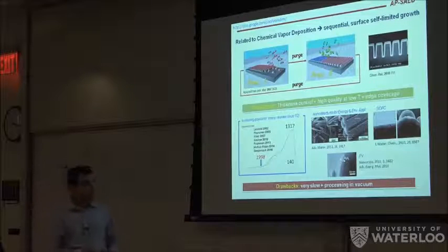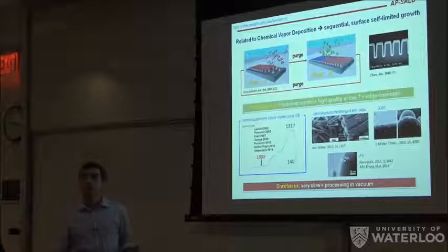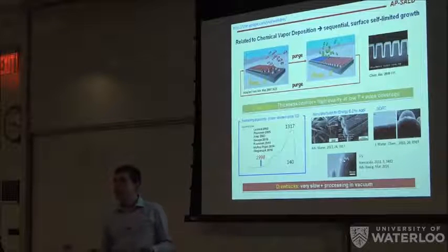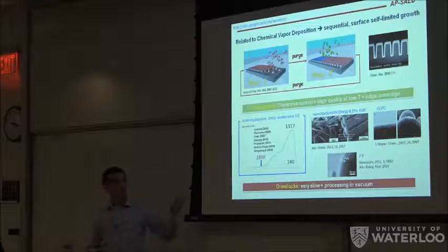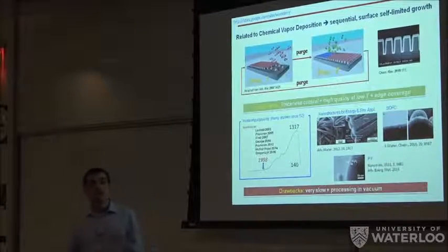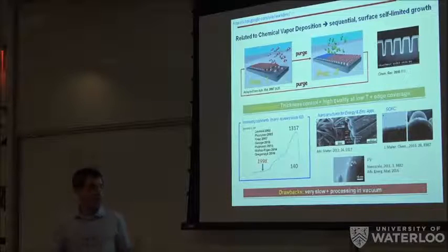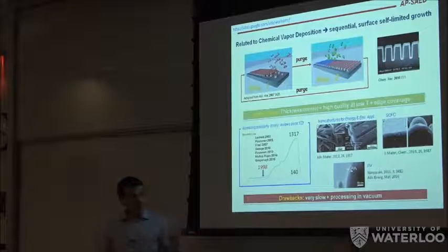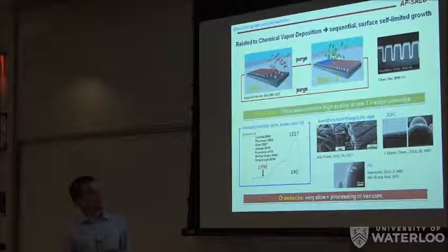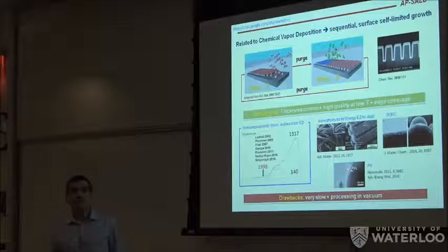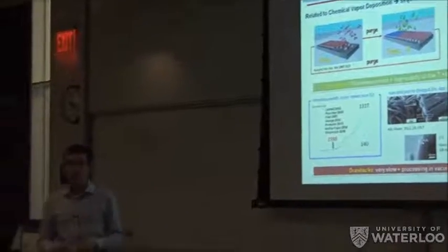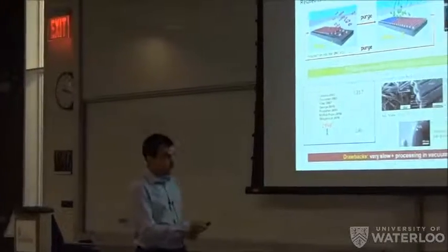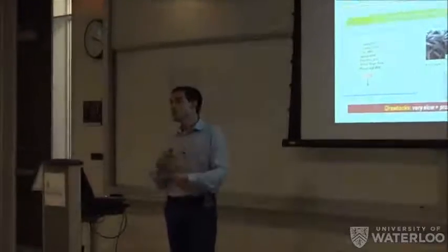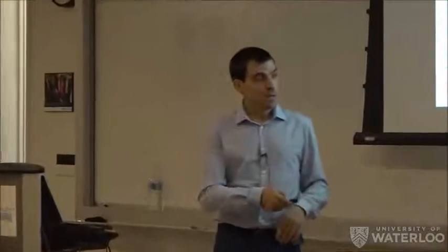And there's been a lot of papers and reviews dedicated to the technique. It's very widely used now in the laboratory, especially with the coming of nanoscience and nanotechnology. It's become very useful because it allows you to nano-engineer the surface and the interfaces, which is very important for devices as well. But nevertheless, it has two main drawbacks which have prevented it from being widely applied in industry. The first one is that it's very slow, because of course you have this sequential injection and purge of precursors. And the second is that it's mostly processed in vacuum, and that makes the scaling up quite more complicated and expensive.